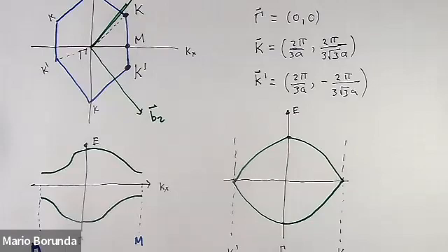In this direction, the two bands are touching, so there's no band gap. But they're also going to zero. So it's conducting because there's no band gap, but it's also not fully a metal because there's nobody here to conduct, even though it's a conductor. So if it was perfect, it would be almost a metal, but not really. Okay, so those are subtleties. Metals would have some states here that are ready to conduct, but this graphene does not.